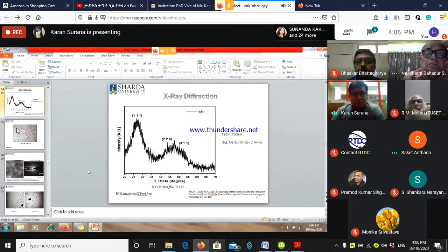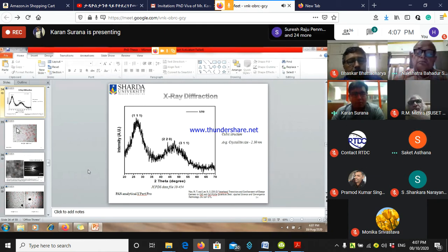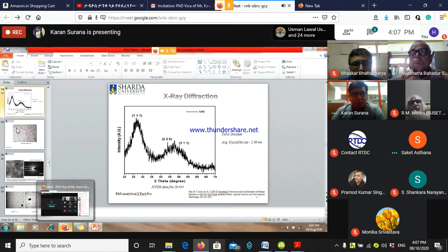Yes, sir, the Scherrer formula for calculating the crystallite size: D equals K lambda by beta cos theta, where beta is the full width at half maximum, FWHM.